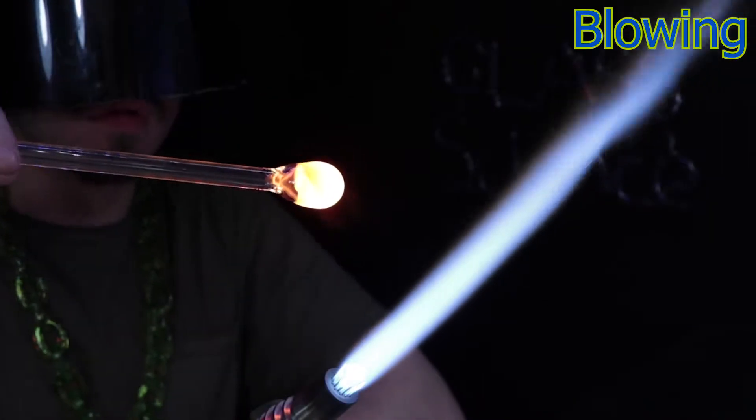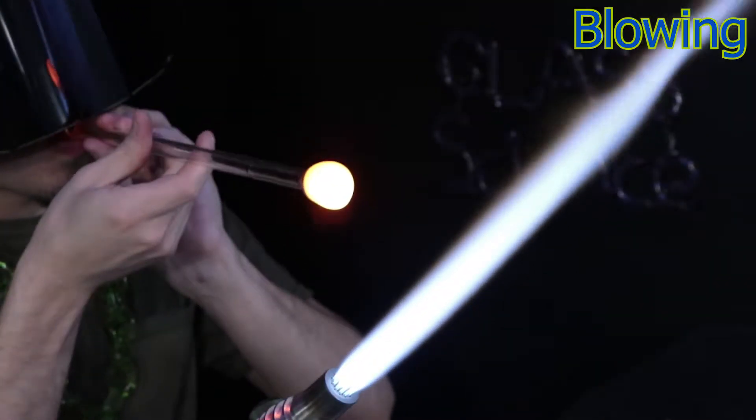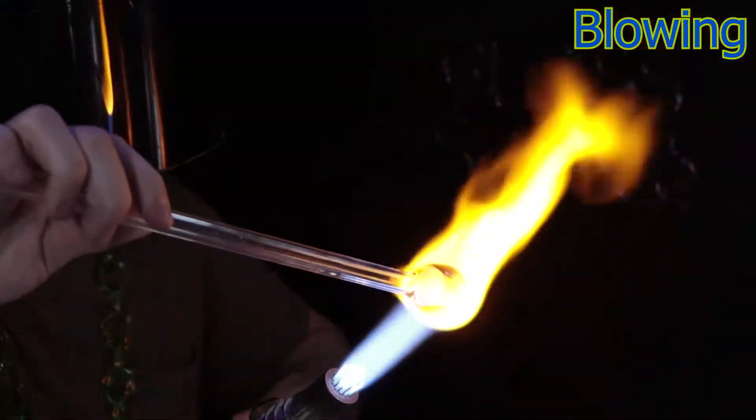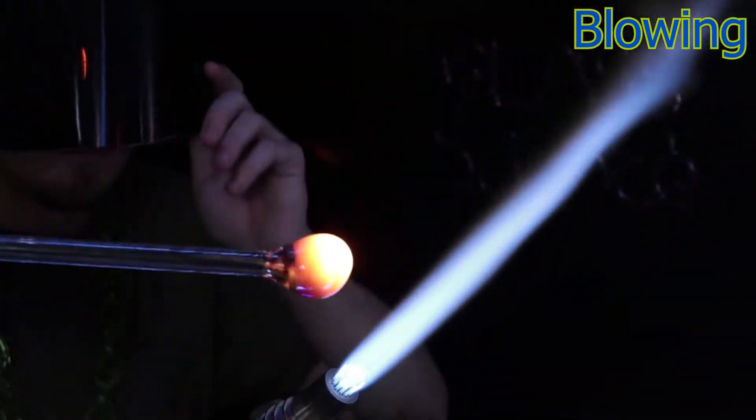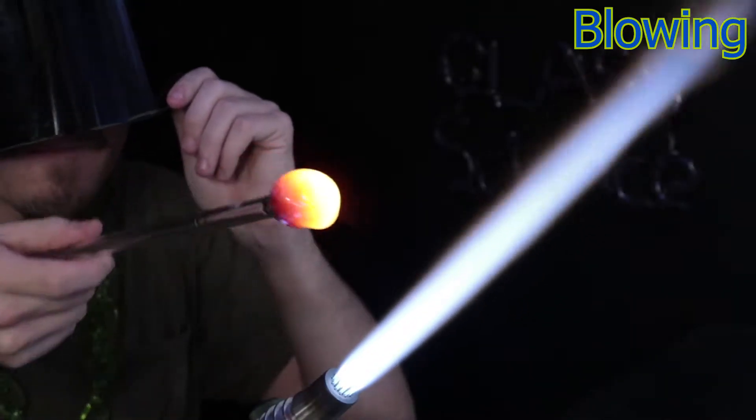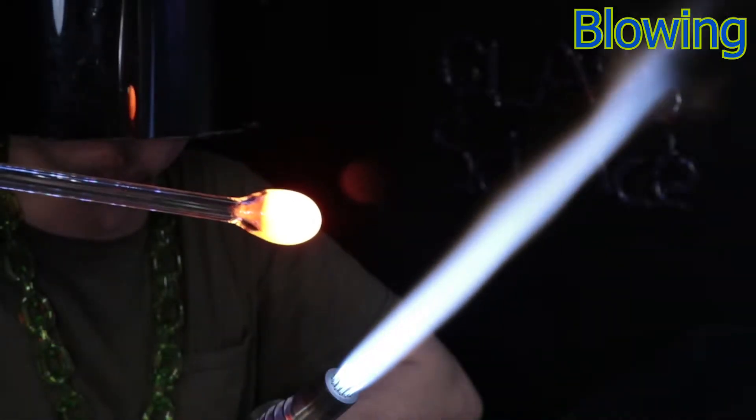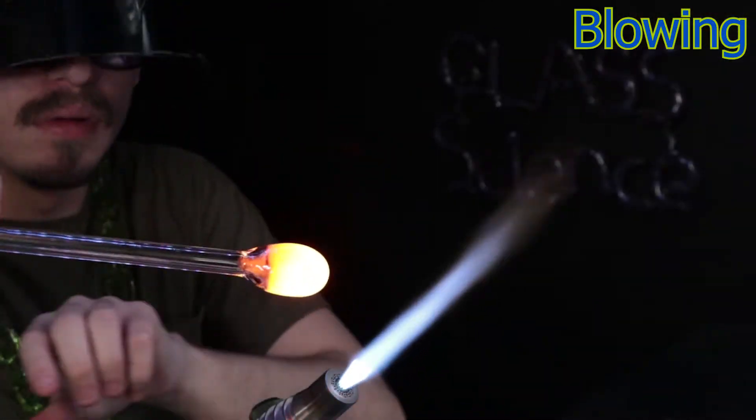Also, normally when you're blowing out a bubble, you would want to wait about four or five seconds for the heat to radiate through the bubble. In this case, with a solid color blowout, you want to start blowing immediately. Just because that glass is so thick, that it's very, very difficult to expand it.